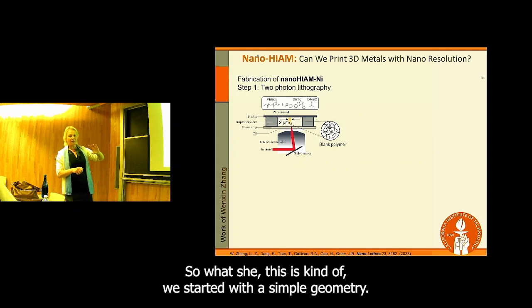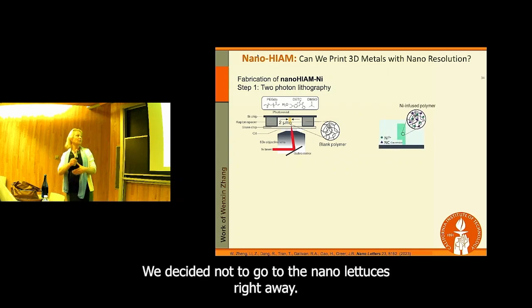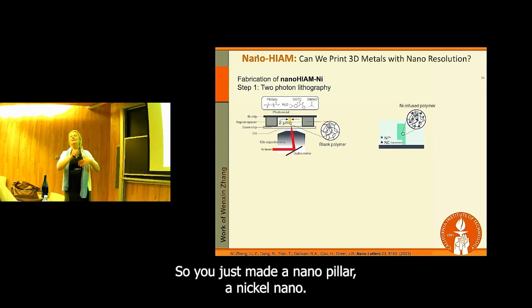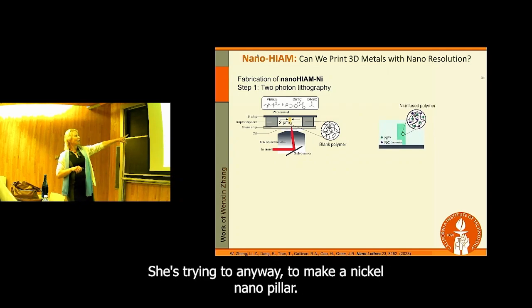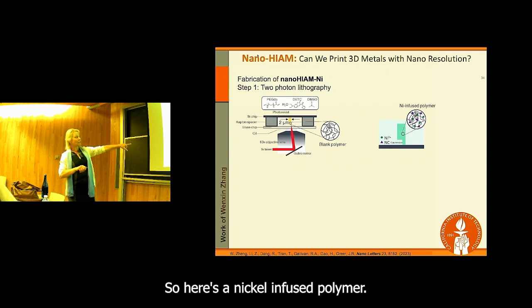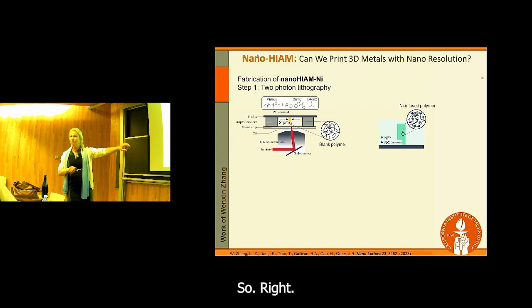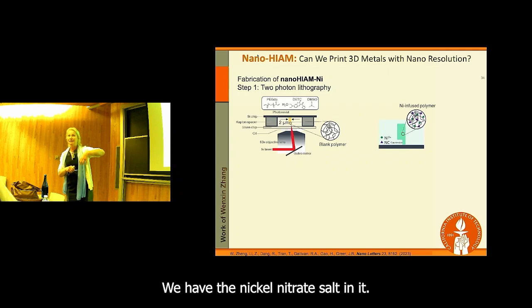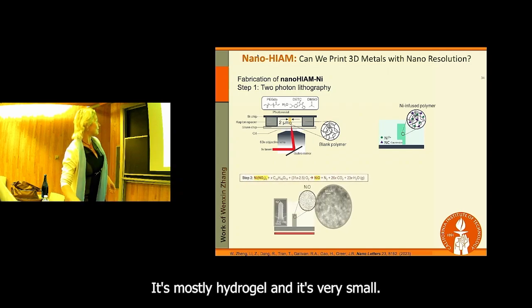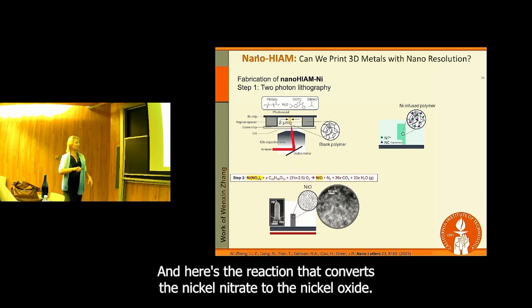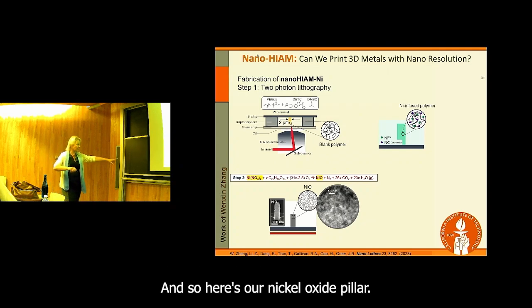So we started with a simple geometry. We decided not to go to the nanolattices right away. She just made a nanopillar, a nickel nanopillar. She's trying, anyway, to make a nickel nanopillar. So here's a nickel infused polymer. So we have the nickel nitrate salt in it. It's mostly hydrogel, and it's very small. And here's the reaction that converts the nickel nitrate to the nickel oxide. And so here's our nickel oxide pillar.